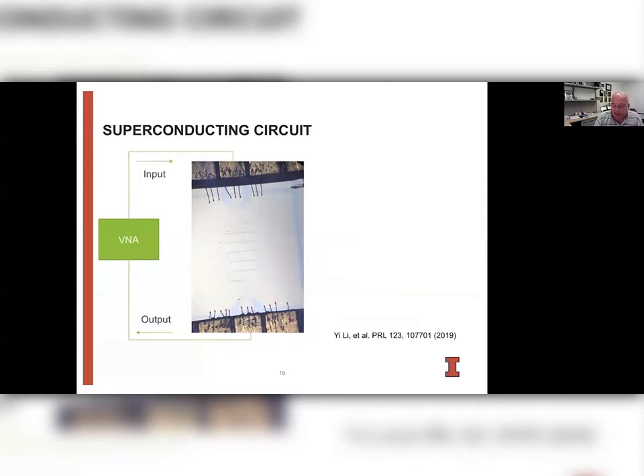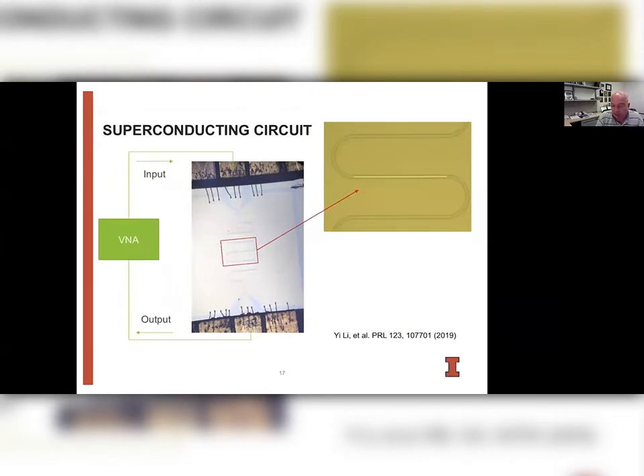So let's go back in detail once more. Here is a larger overview of the whole system that we investigated and how we contacted it for our microwave transmission experiments. Then if we zoom in here in the center, here we see the permalloy structure grown on top of the signal line of the superconducting resonator. And if you would look from the side, you would see that we have a small insulating layer between the niobium nitride and the permalloy. So we have some electrical insulation between the two. And the permalloy structure is slightly narrower than the signal line of the superconducting resonator to ensure a homogeneous field distribution.